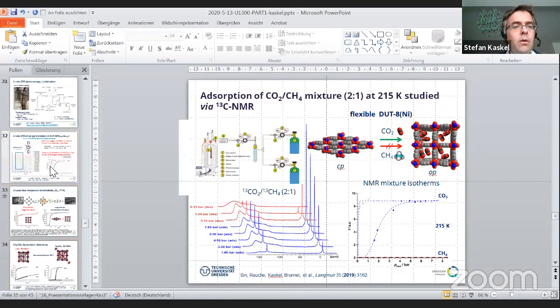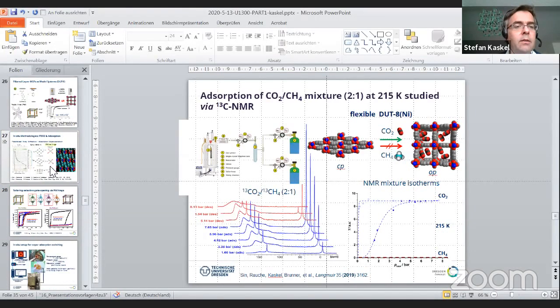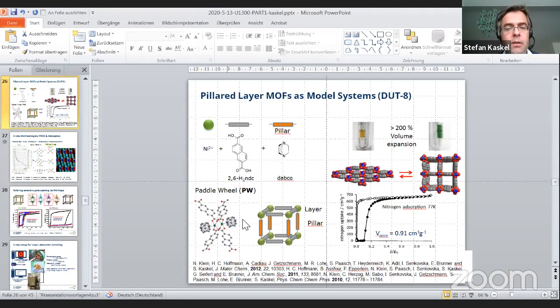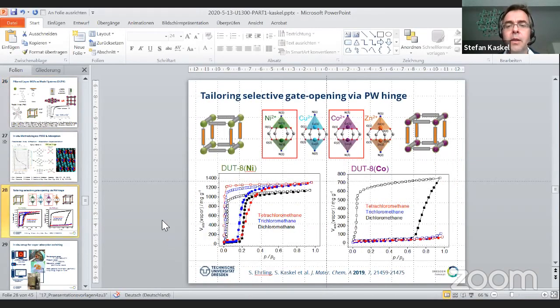In this case, in our view, we think it does not, because the nickel is saturated and has no open metal sites. You can see this in this slide here. The nickel is coordinated to the carboxylates and to the DABCO and has no open metal sites. So there's no direct interaction. The closest interaction is basically to the carboxylate oxygen. And in this way, it might affect the adsorption enthalpy a little bit. But to our knowledge, the strongest effect on tailoring the switchability, which I've shown here, is the deformation energetics. So the question is how easy it is, basically it's like a spring. You can imagine the hinge is connected with a spring, and the spring is different for the nickel and for the cobalt system.